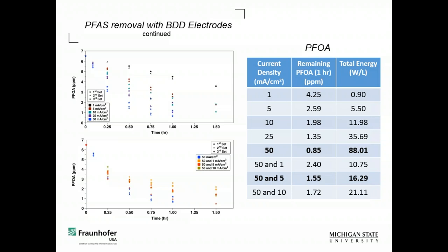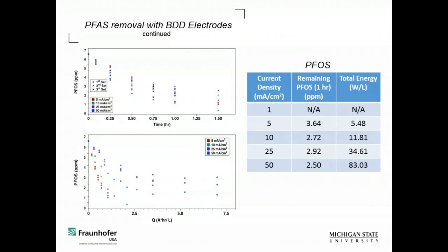And sure enough, if we run this 50 milliamps per centimeter squared for 15 minutes, reduce it to 5 for the remainder of the time, we have about twice as much PFOA left after 1 hour. If we run it for a half hour longer, we get below this, and we're saving about 5x on the energy. So even though this still is too much to do as an end of pipe treatment, we still want to design a way where we can save as much energy as possible.